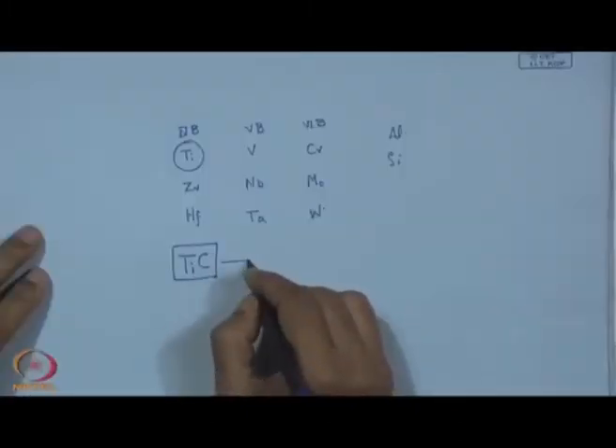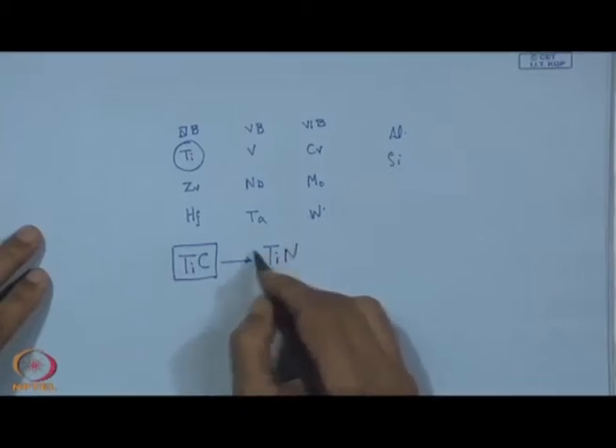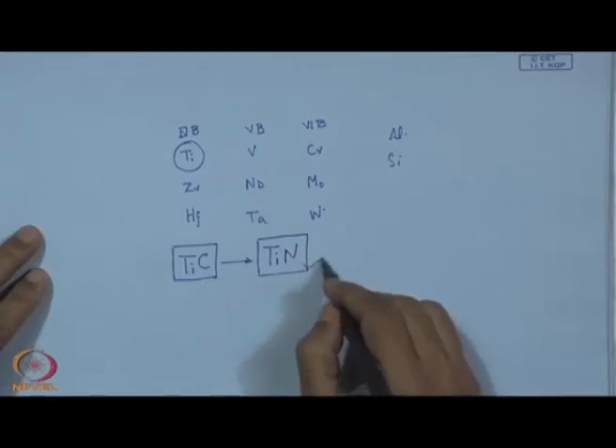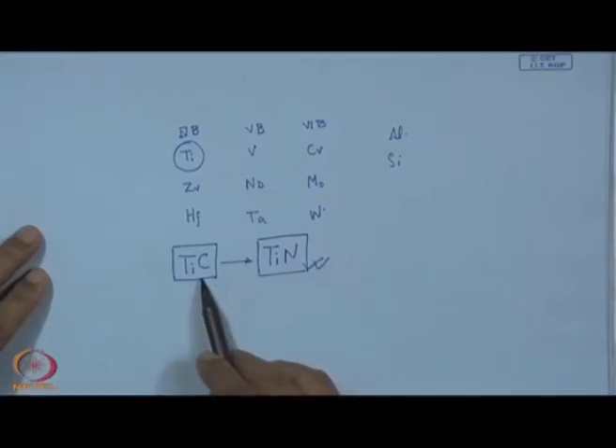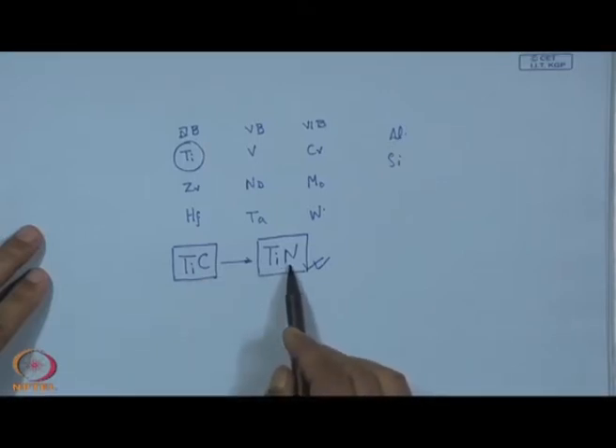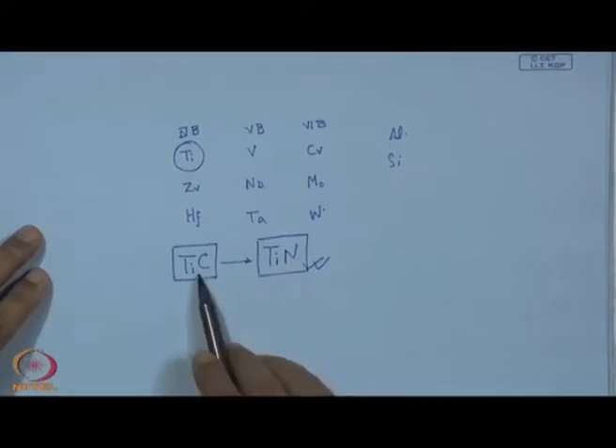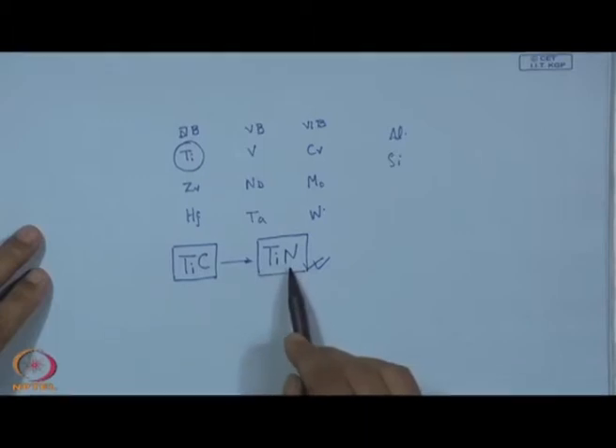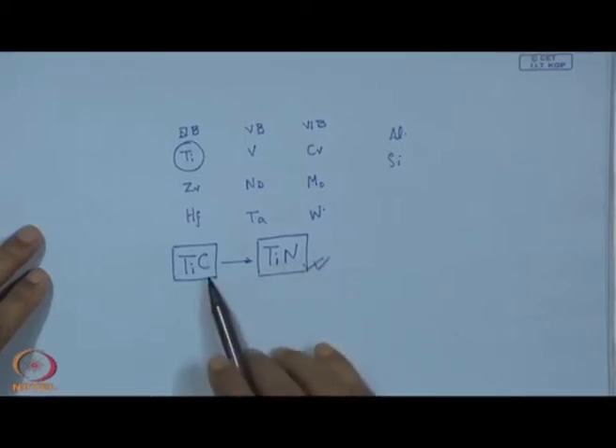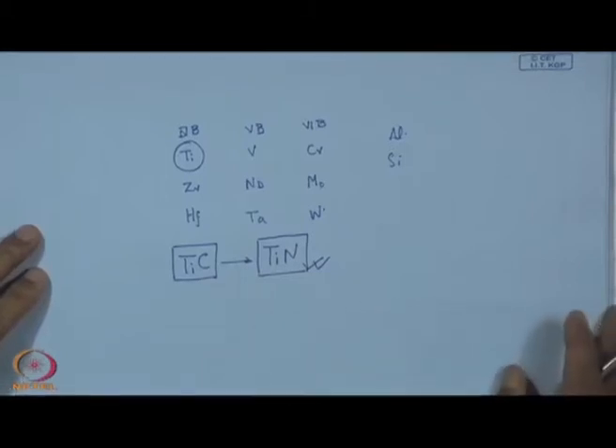Now, if we consider TiN against this TiC, then we find that this has an improved property in comparison to TiC, because of the simple reason this is more chemically stable than TiC, its anti-welding property is better, and diffusion of carbon, say for example in steel, will be more than diffusion of nitrogen. Or we can say in this way that titanium nitride is more stable against steel than titanium carbide, and we can identify many more applications where even this TiN is found to be much more effective, high performing than TiC.